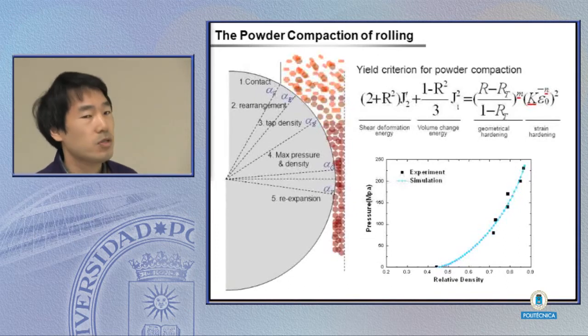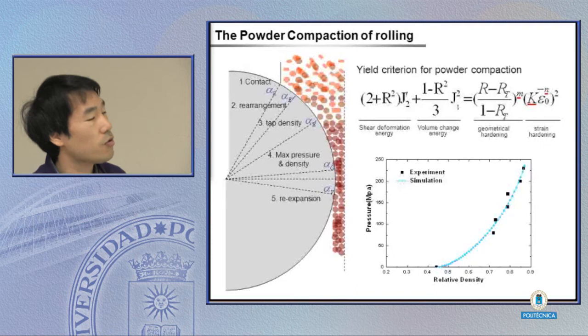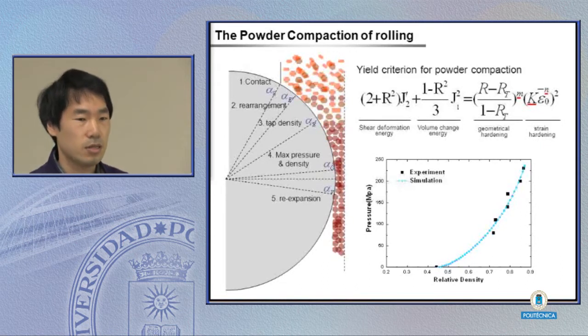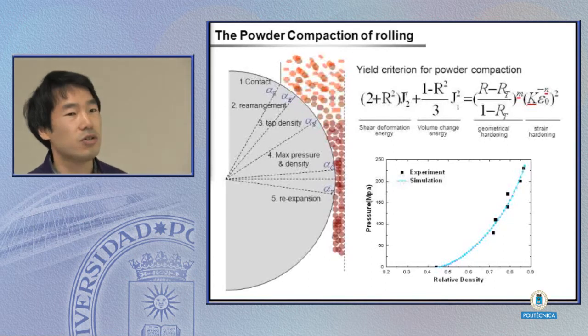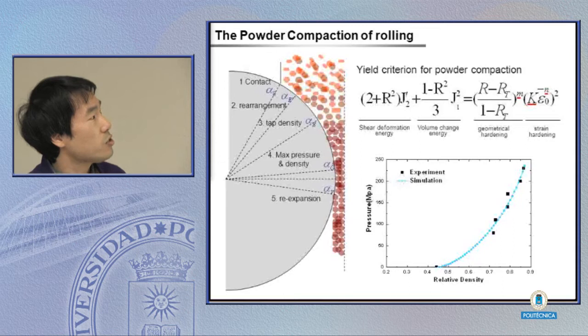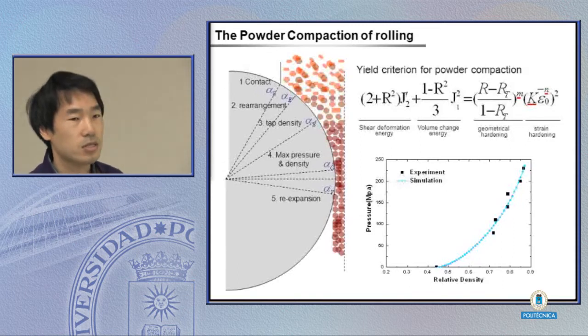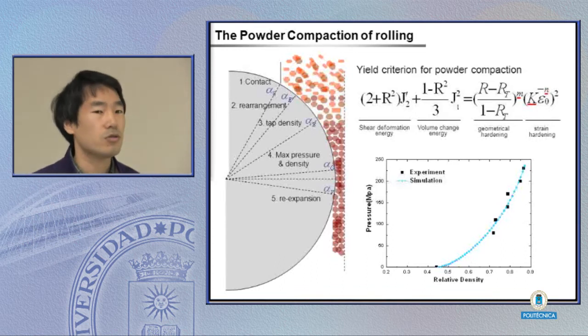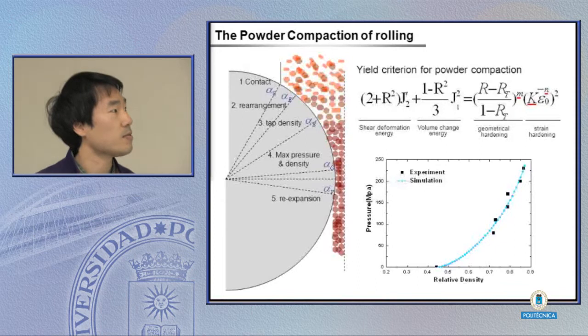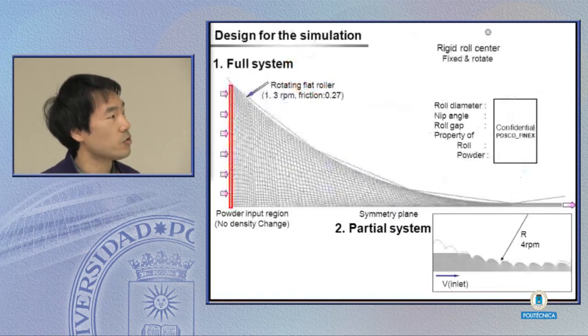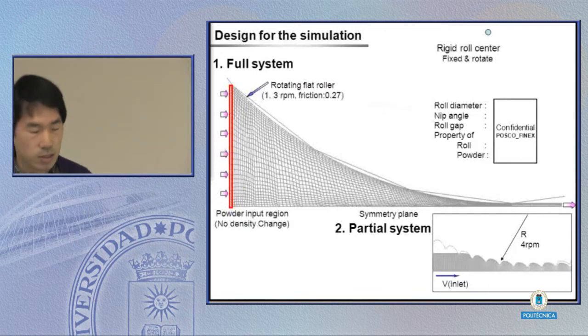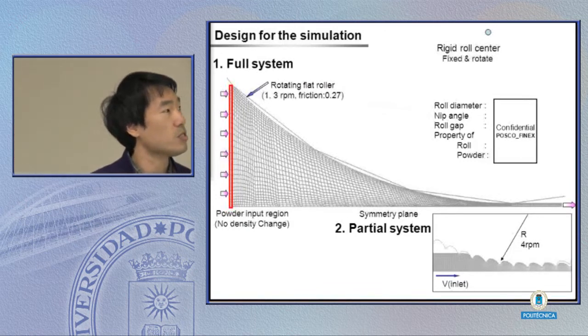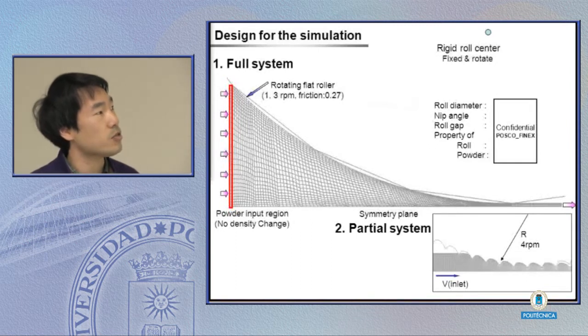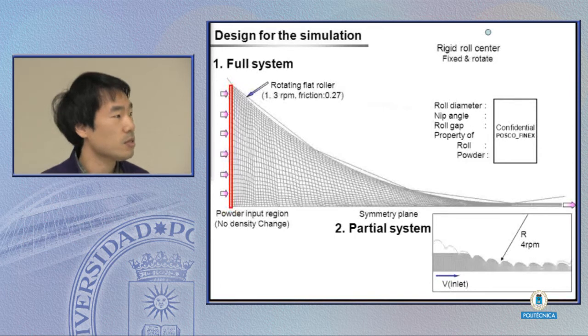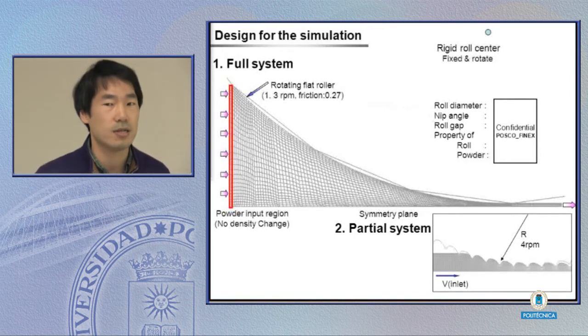First, I can show you the powder compaction by rolling. When the powder contacts the roller, the voids inside the particles are reduced due to rearrangement. And as soon as the powder density reaches the critical density, the powders start to deform plastically. As soon as it passes through the roller gap, it re-expands a bit due to elastic deformation. All of this procedure can be simulated by this kind of criterion with three unknown parameters. The parameters can be obtained from experimental data, like this.